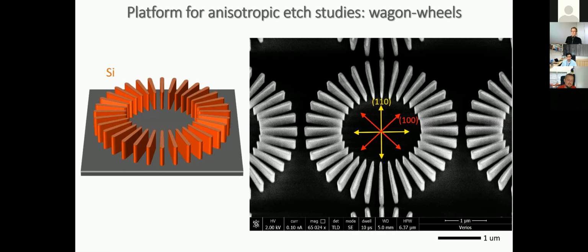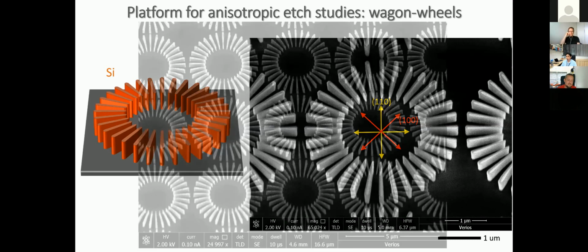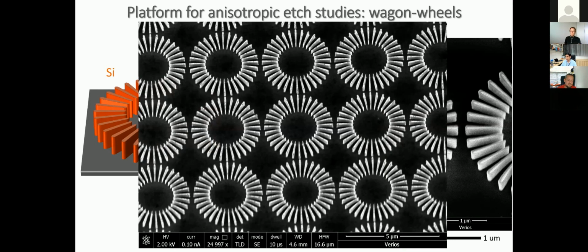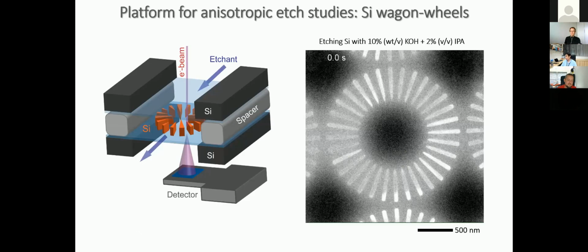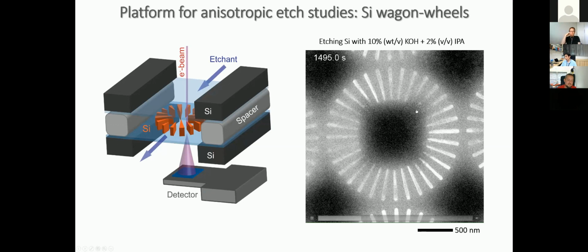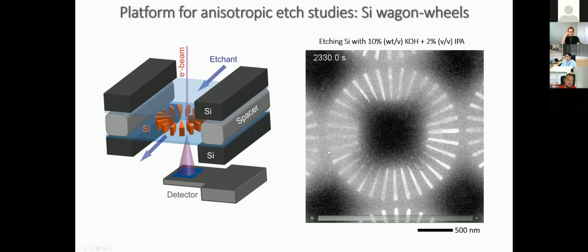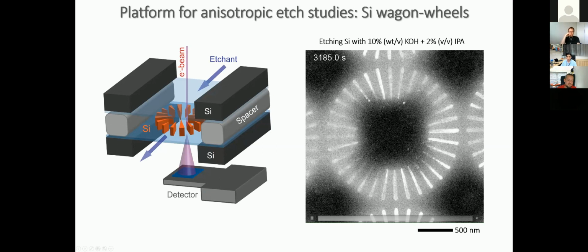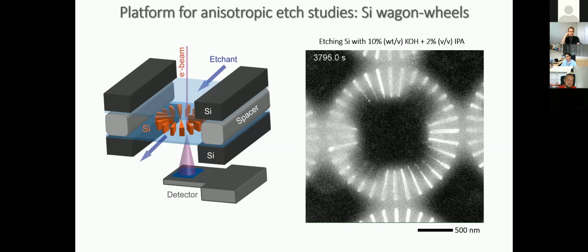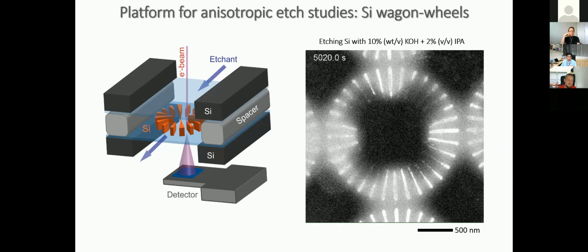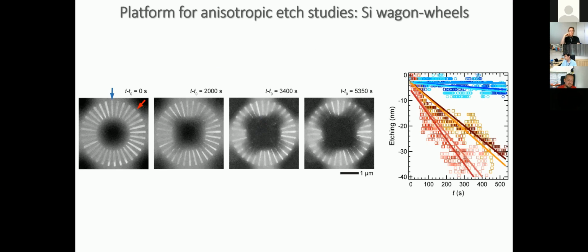And you can do it across a large wafer, and you pattern this on a silicon oxide membrane, and then you can watch. This is a movie of this etch happening. Again, you see very selective etching, right? So it's etching along very certain directions and not along the other directions. So you can really control, and then you see these small things falling apart, and you can do a lot of quantification. I'm not going to go into the details, but at least you can not only visualize, but also quantify what's going on at the nanoscale.